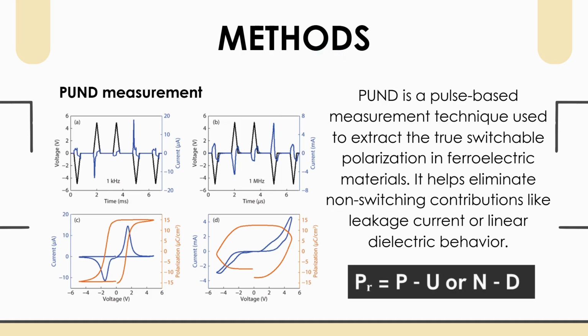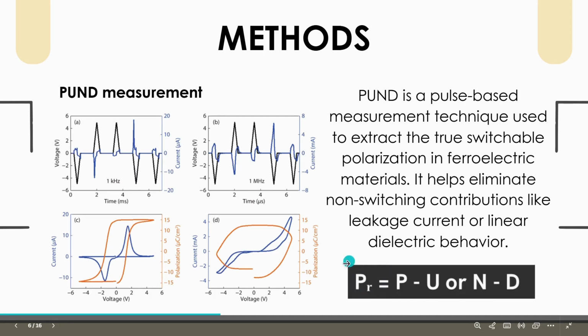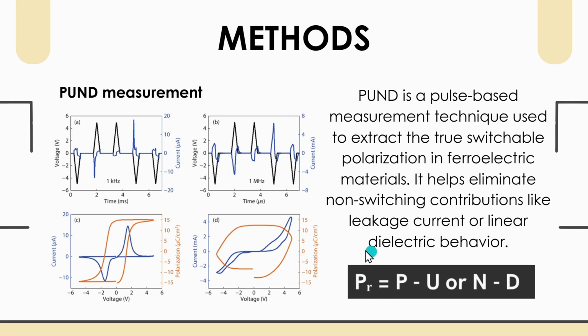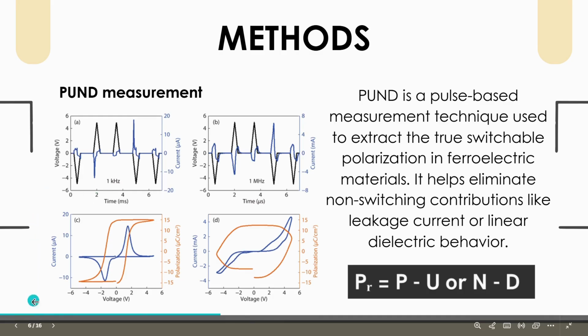Now with PUND measurement, to measure switching correctly, I used a method called PUND, which stands for positive up negative down. A voltage pulse is applied to the sample and it compares the charge when switching happens and when it doesn't. So we can see here that we have the positive up and the negative down. And this way we can know the real switching charge and ignore things like leakage or background signals. Finding the difference of the signals gives us a clean delta P, or the PR, the true switchable polarization. And these figures are an example of what we expect to get.